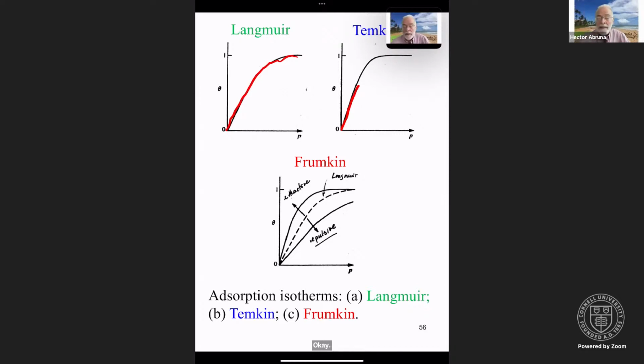For those of you who are biochemists, it's basically like a Michaelis-Menten type profile. Now we can look at the adsorption isotherm for Langmuir and compare to attractive or repulsive interaction. Here the Langmuir is this line. An attractive one means that for a given driving force, I have a higher coverage. For a repulsive one, I have a lower coverage. One way that it's useful is to start assembling an isotherm at relatively low driving forces or low concentrations, because very close to the origin they basically converge, and then you can get a sense of which direction they're going to go.